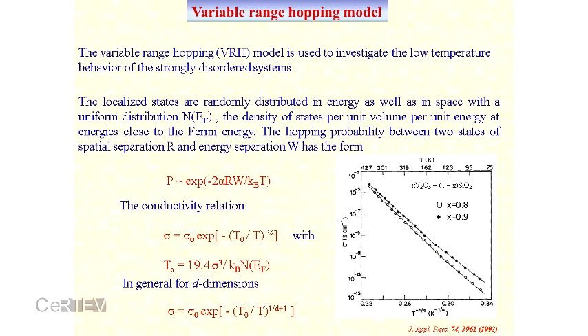Here, he calculated theoretically the probability of the electron to hop from one position to another, and he arrived at an expression for conductivity. We can see it is not an activated process. It does not contain any activation energy, but rather its temperature variation follows the T to the power 1/4 law. You can plot sigma as a function of T to the power 1/4 and get a slope. You can get two slopes, of course. Here is the high temperature region, here is the low temperature region.